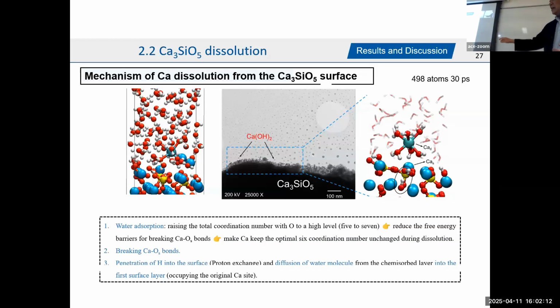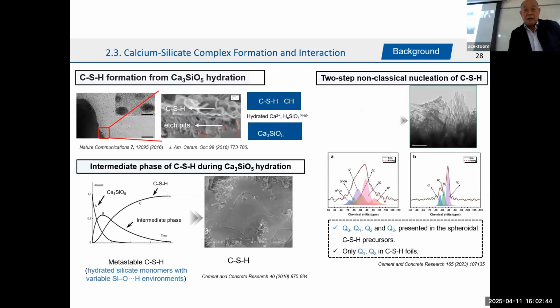And this graduate student mentioned, you see from adsorption, you have the connection with the oxygen from the water, and with the increased connection of the oxygen from the water, the bond between the oxygen from the C3S and this oxygen breaks, and finally they can move out. So this is the process. So after this calculation,